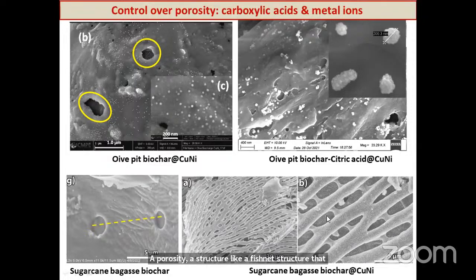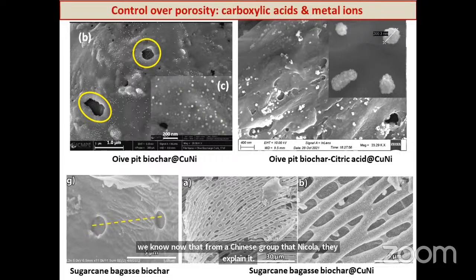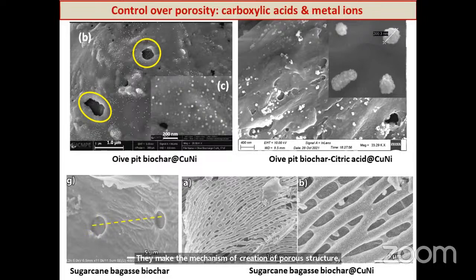If you check whether it works for copper, it does not work. Only nickel provides this fishnet structure of the biochar during pyrolysis, and this has been well documented in the literature. We know now from a Chinese group, who explained the mechanism of creation of porous structure, that a nickel precursor is used to obtain immobilized nickel nanocatalyst.